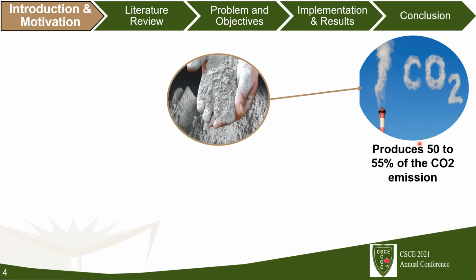This is because the main source of CO2 emission in cement production is the calcination of raw material, which produces approximately 50 to 55% of the CO2 emission, while burning fuel produces 35% and transportation produces around 10%. Cement substitution is reported to be the most efficient way to achieve a significant reduction of CO2 emission.